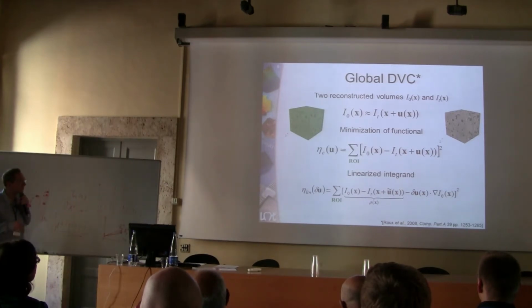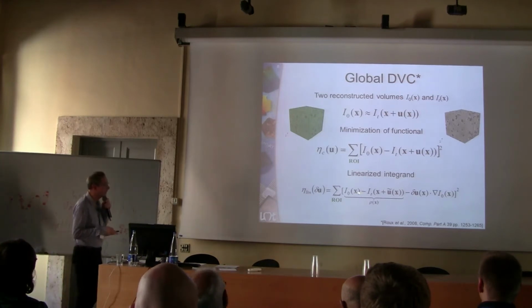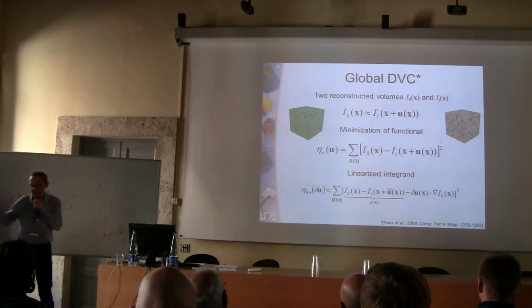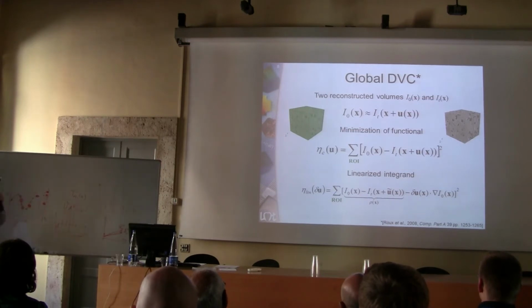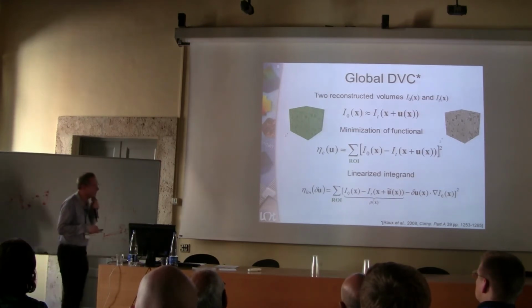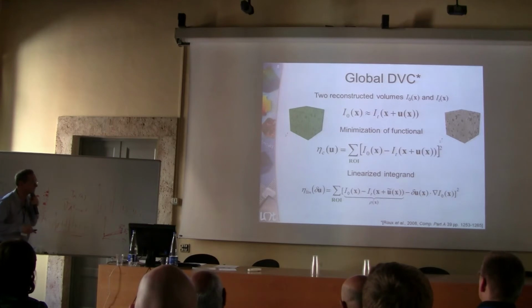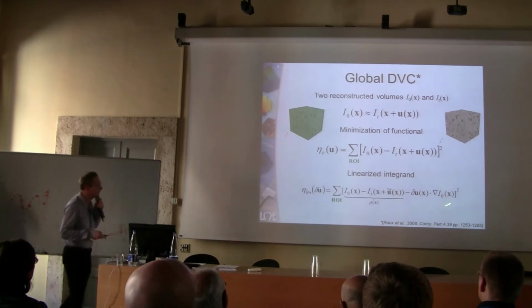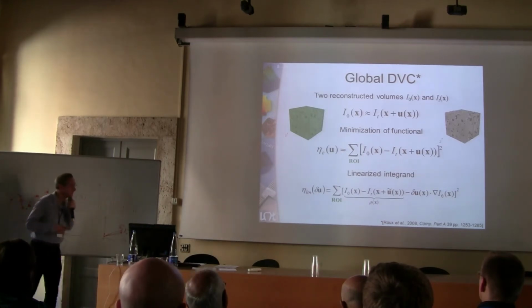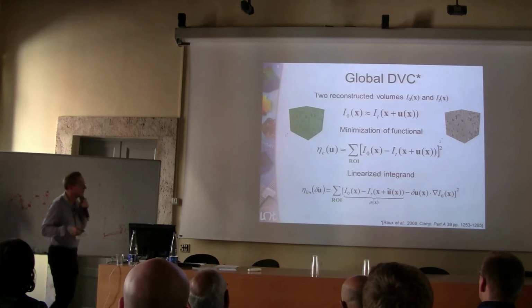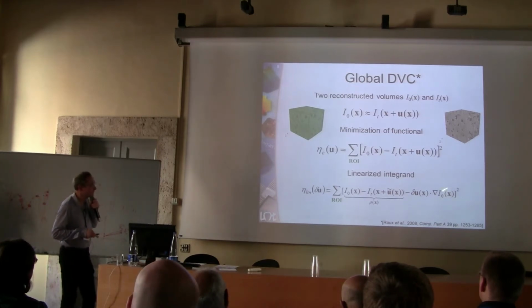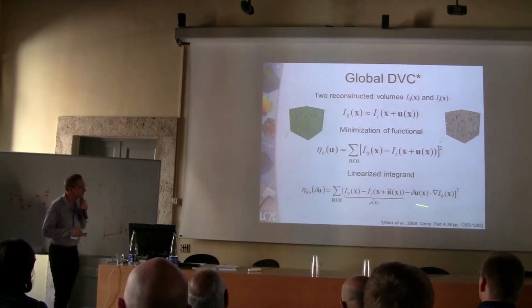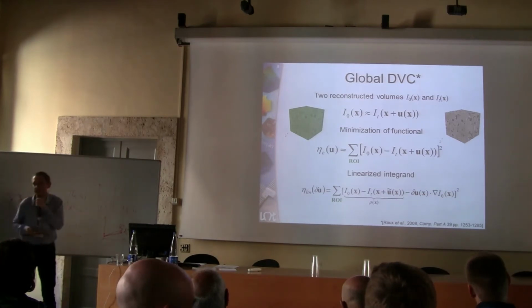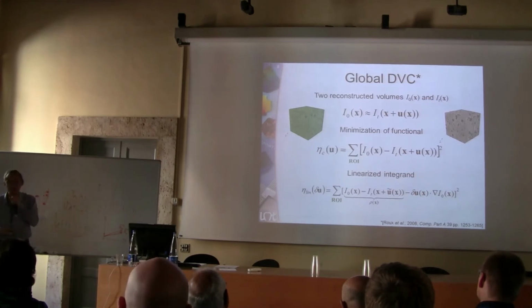If you consider an iterative scheme, at an evaluation u tilde, and ask what is the best correction to apply, you perform a first order Taylor expansion of the integrand. What you end up with is the correction you're after and the gradient of the original image in the approximate solution, which tells you that what you're looking for appears as a scalar product of these image gradients.